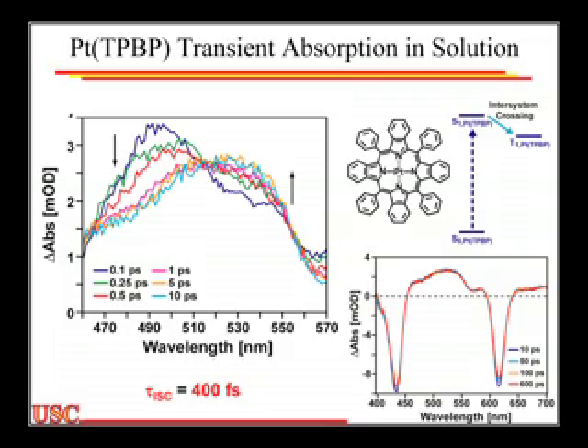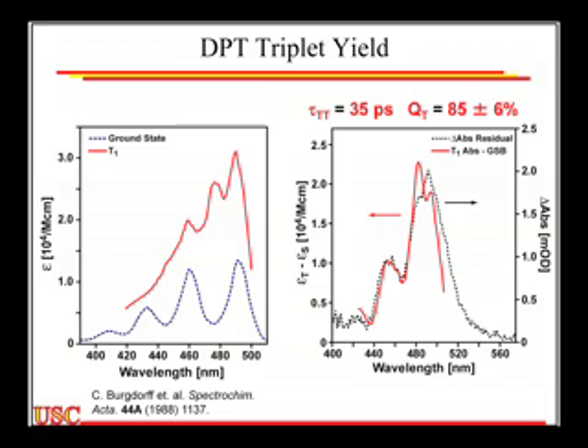So now what happens if I put this into DPT? I pump it, and I already know that this intersystem crossing is about 400 femtoseconds. So now, promptly within 10 picoseconds, you can see that I'm getting a big bleach for the Soret and the Q bands, but unlike before, remember at 600 picoseconds there was no change. In DPT, I lose the whole signal, and that's because in DPT I intersystem cross to the triplet, then this transfers energy to the triplet in DPT. If there's no DPT around, it sits in its triplet excited state forever. If I put DPT around, it transfers a triplet back to DPT. The time constant for that's about 35 picoseconds.